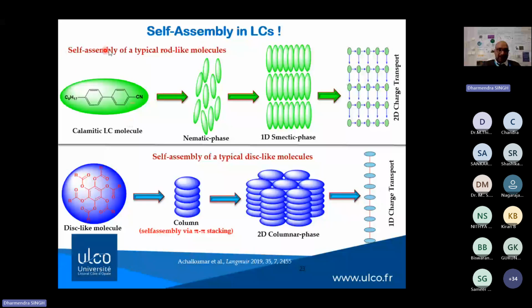So here you could see how the rod-like molecules are self-assembled. If you take a rod-like molecule, such as a cyanobiphenyl-like molecule, and when they are in a particular condition, they can constitute the nematic phase or smectic phase. If you talk about the smectic phase, these are molecules which have a particular orientational order, and they are also arranged in a layer structure, so they will have the positional order as well. So here, these molecules are forming the one-dimensional smectic phase, and following the one-dimensional smectic phase, they exhibit two-dimensional charge transport along the long molecular axis and along the short molecular axis as well.